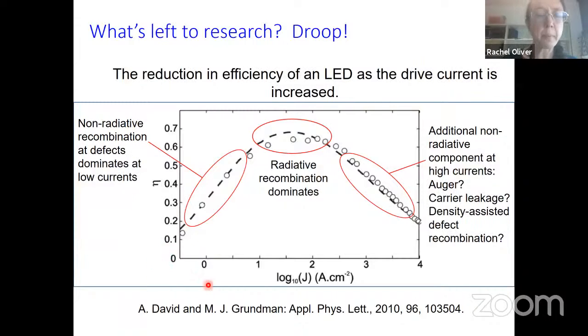So what's going on? Well, if we make a curve of the efficiency against the drive current here on a log scale, in fact, as current density, we see low efficiencies at the lowest currents. At moderate currents, we see really quite high efficiencies. And at the highest currents, the efficiency drops off again. Now, what's going on at the low current end is that we do have some non-radiative recombination at defects, and that is tending to dominate the low current end of the curve. As we put in more carriers, though, we see the radiative recombination start to take over. The question is, what's happening at this high current end?